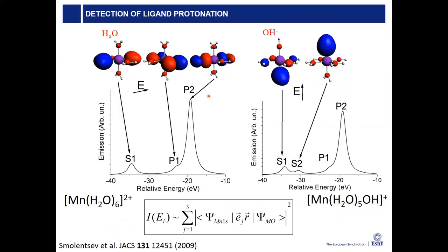It goes further, you can even see this in model calculations done by Grigory Smolentsev, who is now at the PSI. If you have a hypothetical system of manganese in the center here and six water molecules around, you can detect in the spectra whether one of the six water molecules is missing one proton. So if I replace a water molecule with a hydroxide, then this shows up in the spectrum. Why? Because if I remove the proton, the binding energy of the 2s electron in this oxygen will change. And I can assign that this molecular orbital, mainly localized on this oxygen, has a different binding energy and thus a different fluorescence energy than the water molecule on the other side. On the other side, I still have water with two protons and the energy is different.